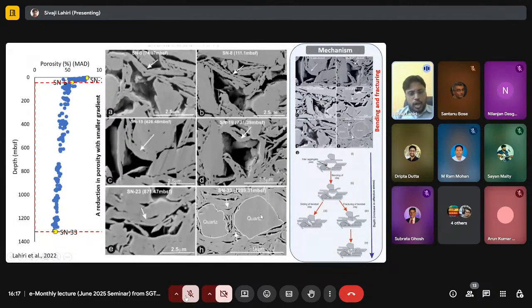Now, I would like to concentrate on this particular microstructure. So this is a very interesting microstructure. Here you can see there is a quartz silt particle, there is another quartz silt particle, and in between them, we can observe there are some small clay particles. On top of that, you observe there is an aggregate of clay particle, and this aggregate of clay particle actually got bent. Now, interestingly, if we look at the number of small clay particles present within this small space in between two quartz silt particles, you can see there are only 4 small clay particles present.